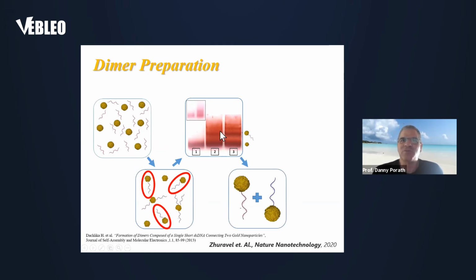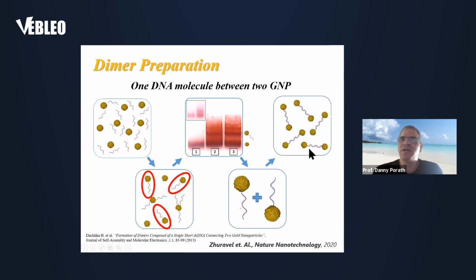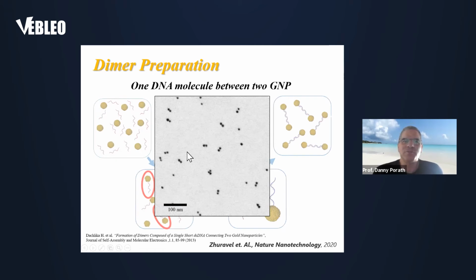Then we can really cut the band and extract the structures where you have a nanoparticle and a single strand. We can do the same with the complementary strand, and in this way we get the dimers with a single DNA molecule connecting the two nanoparticles. And indeed, when we deposit them on the surface, we can do scanning electron microscope imaging, and we can see that most of the structures are indeed dimers.